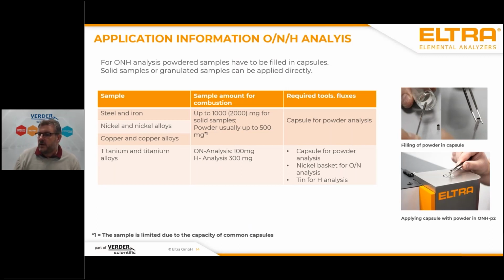For steel and iron, we again have a maximum amount of about 1000 milligram. It's not limited to powder or solid samples. You can also apply drilled samples or chipped samples. It's no problem. For titanium analysis, you have to consider the ASTM regulations, which means 100 milligram is the maximum for N analysis and approximately 300 milligram is the maximum for hydrogen analysis. This is not due to our analyzers, but just due to regulations of the standard.